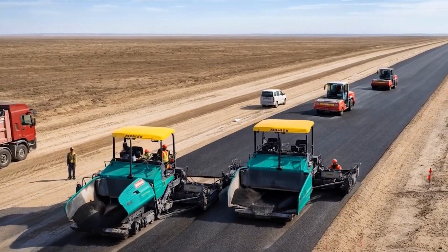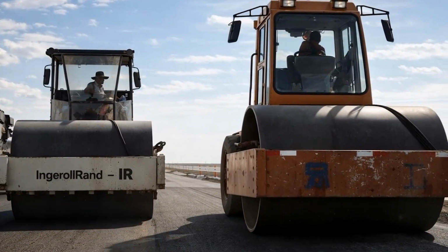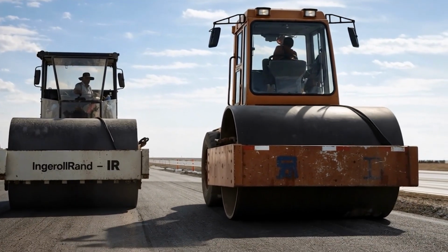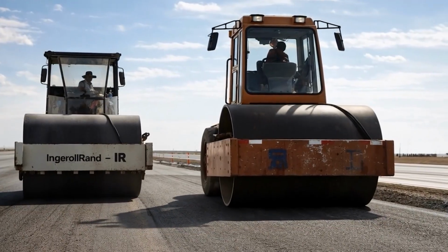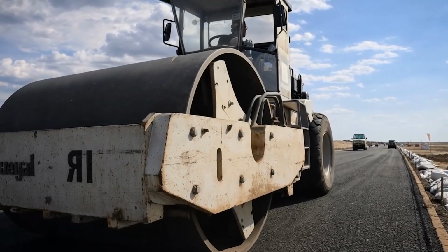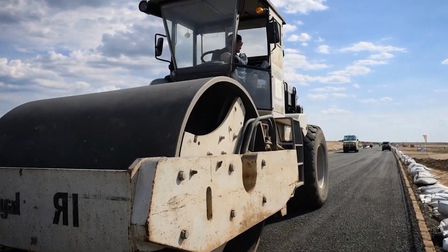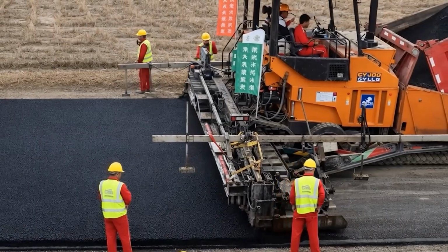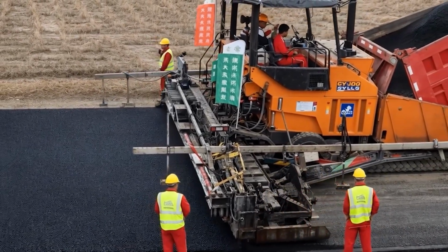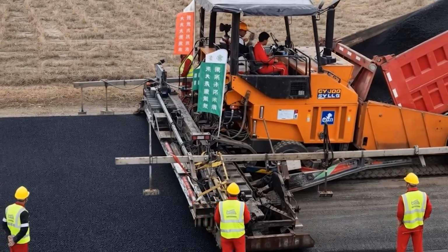Temperature sensors on the pavers monitored the condition of the pavement in real time. If the asphalt temperature dropped below 140 degrees, the work was immediately stopped. Otherwise, cracks could appear. After cooling, smoothness was checked with laser systems, allowing a deviation of no more than 3 millimeters per meter.